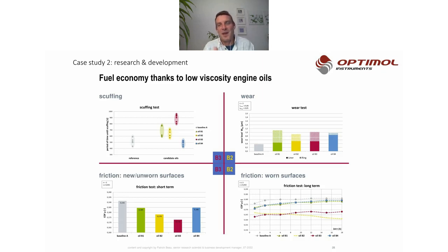If you're using a very hard coated piston ring and a very thin oil with low viscosity index, you will end up with more wear in your system. It was very new information, and typically it will take a while to ride all the trucks in the field to find out that your system will be totally worn out. And then, talking about friction, you will end up with data, and you can display your data for friction tests. And we do have 2 procedures.